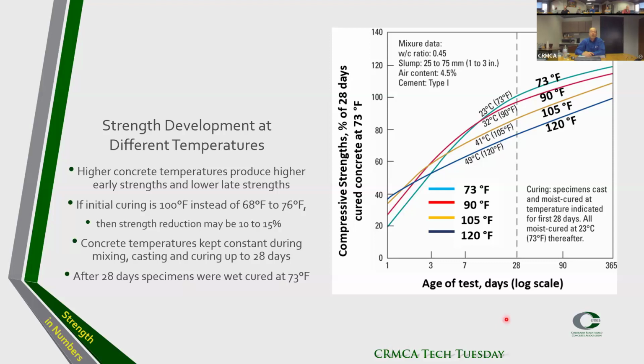You see the dark blue line, around 38, takes off at the beginning, one day, but it tapers off. And then what we see is the one at 73F, it's at 20 MPa, around 3,000 PSI at one day, but it keeps developing, and it actually overtakes the other ones already at 28 days, and then it stays on top. So again, what I mentioned at the very beginning, optimum concrete temperature 50 to 60 degrees. This is mainly because we really get the higher 28-day, the higher late strength.